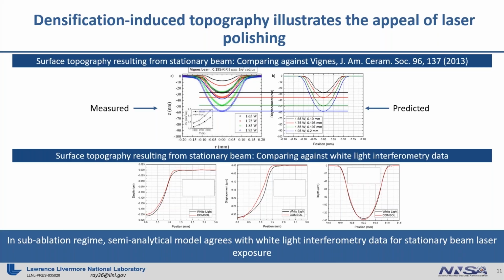And I should throw out the disclaimer that for the semi-analytic model, there's the caveat that it needs to be done in the subablation regime. So this all comes from the change in volume. So if you're evaporating or ablating material, that will be problematic, and then we have to go to a different model that we have. But for the work that I'm showing here, we just wanted densification for the effect of polishing and smoothing. So we were subablation, so that's why this model holds.